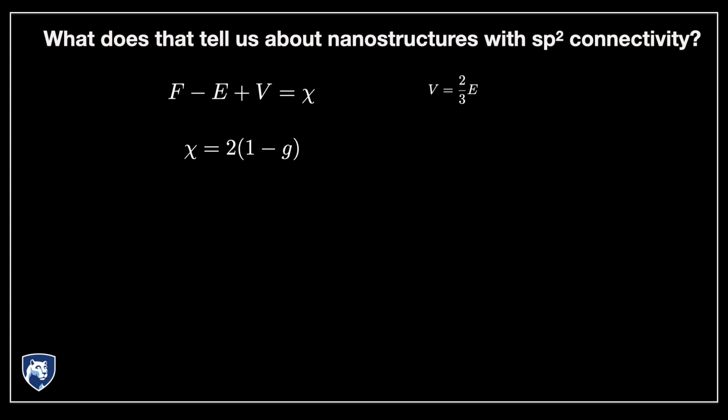So how do we translate the fact that a threefold connectivity is related to this equation? It's actually easy to convince yourself that this is the case. These 2/3 come from the fact that each vertex, so each atom, has 3 neighbors, so it creates 3 bonds, but each of these bonds counts as 1/2 since it is shared with another vertex. So this is the interest of having a recorded screencast. If you have any trouble with this, pause, make a little sketch on a piece of paper, and you will see it directly.